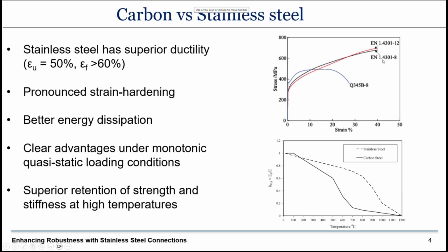As part of the project, we wanted to see to which extent the same advantages are valid under high strain rate loadings, which can happen during an extreme event causing progressive collapse. Another point that we investigated was the behavior of stainless steel under elevated temperatures. So in case of a fire, stainless steel retains its strength and stiffness better than carbon steel at elevated temperatures. And here we can see a curve that was taken from Eurocode 3 Part 1-2, which shows the retention of Young's modulus in this case by stainless steel being the dotted line and by carbon steel being the black line. So similarly for ultimate capacity as well, there is a very large temperature range over which stainless steel significantly outperforms carbon steel.